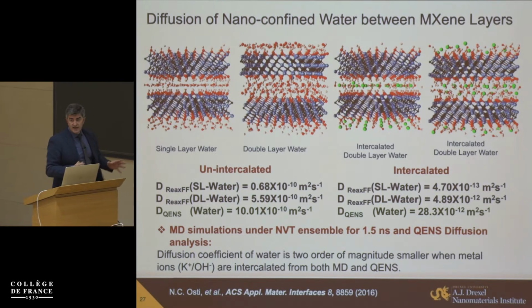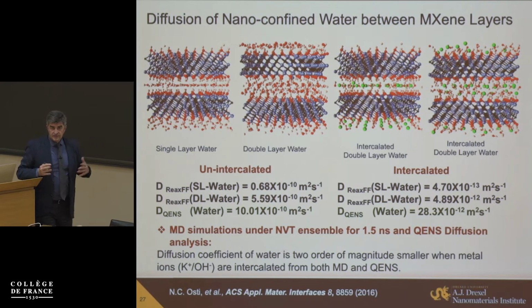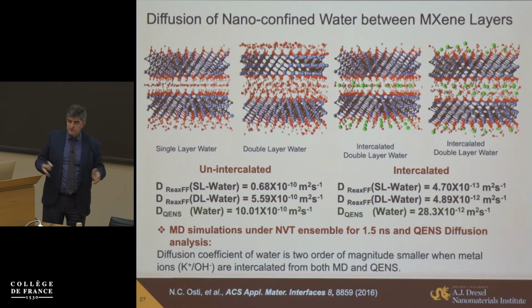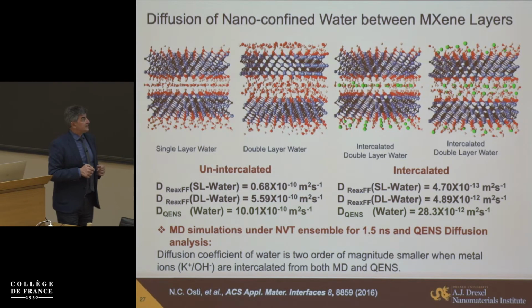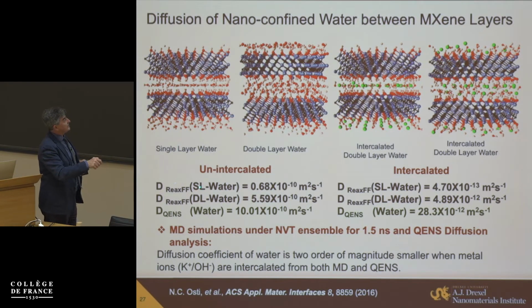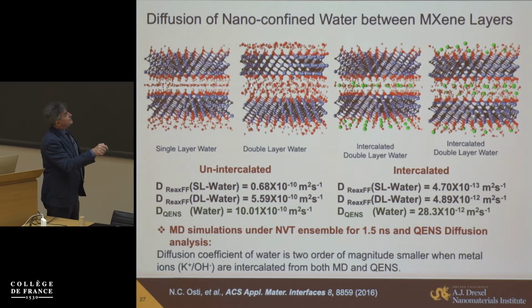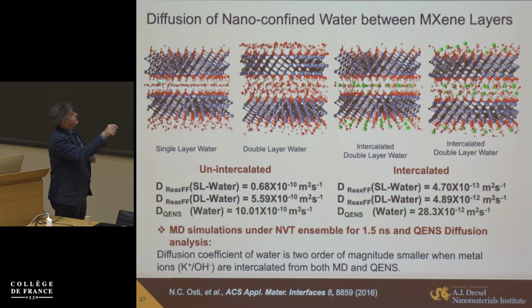Now, we get ions, we get water. And conventionally, people predict properties of solutions, conductivity and everything else, and it's all very well known. But what is interesting here? If you look at water, which is confined between these layers of MXene with strong interaction of oxygen and OH on the surface, you can find that you actually have lower diffusion coefficient of water compared to bulk. But if you get ions intercalated, there is a further decrease by, say, roughly 2 orders of magnitude in diffusion coefficient of water. And we did it by 3 independent techniques, actually.